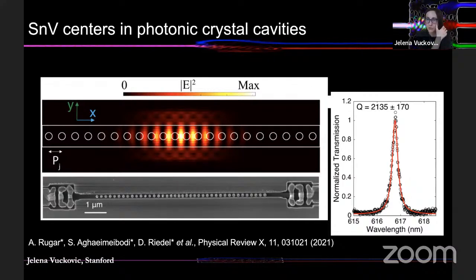620 nanometers as opposed to 740 nanometers. All of the photonics has to be smaller, and all the features have to be smaller, which is why it took us a while, both for us and for Harvard, to develop this new interface. So here is a cavity with a good quality factor.